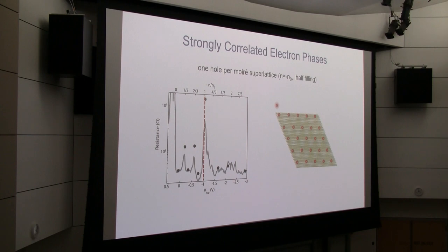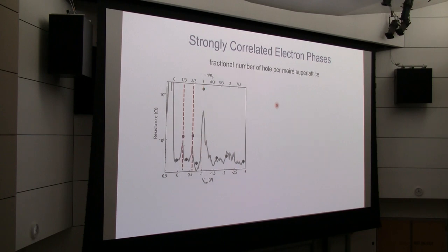But we also notice 2 smaller peaks at partial filling of the system. And it happens exactly at 1/3 and 2/3 filling. Initially, it came as a complete surprise when we observed it experimentally. But once we see it, it's fairly easy to come up with a potential explanation. So this may be the so-called generalized Wigner crystal state.